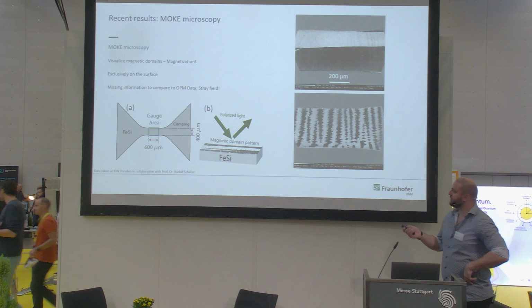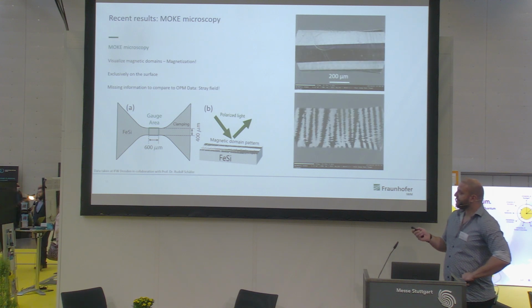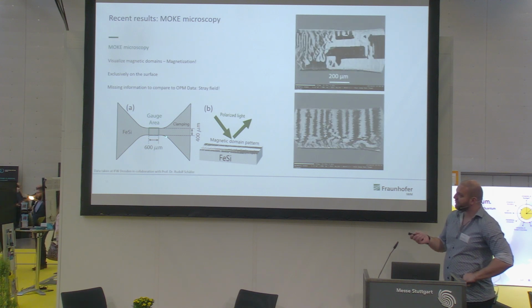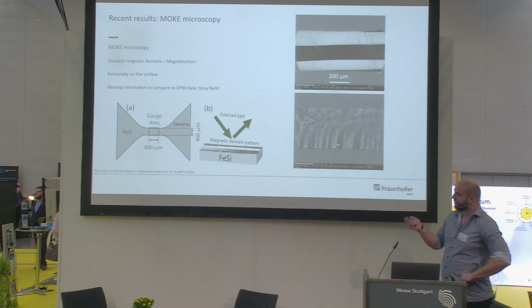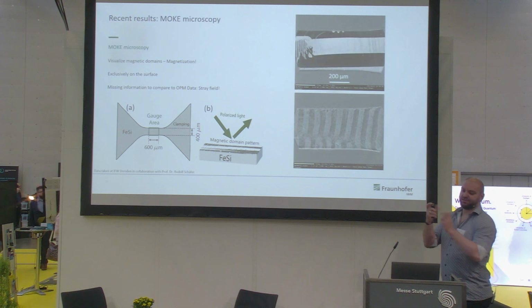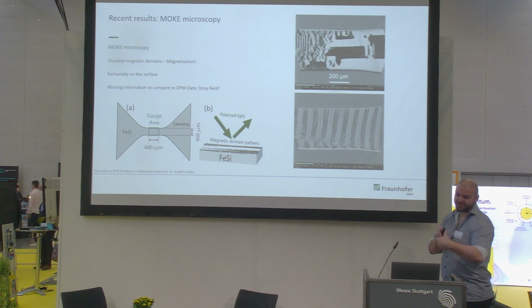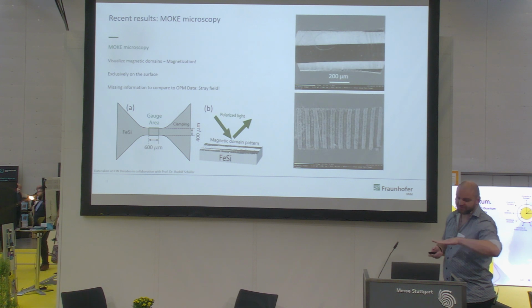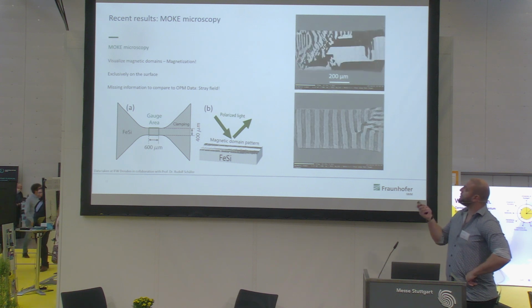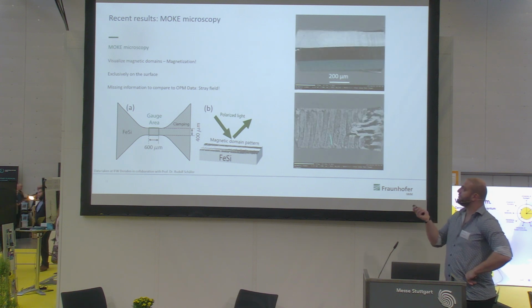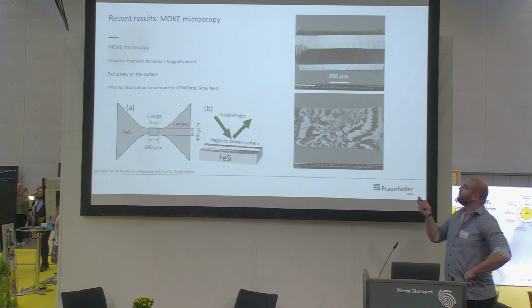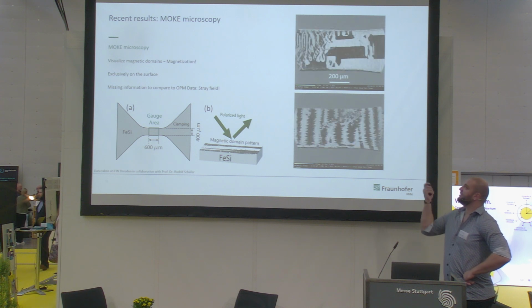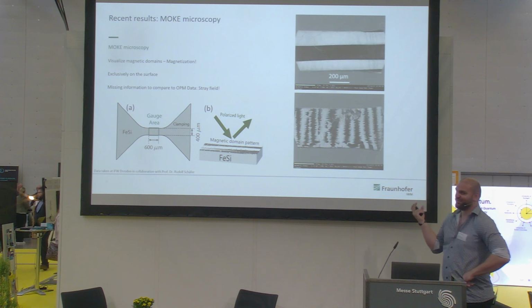So what you can see on the right is the gauge area of one of these samples. We shine polarized light, and it depolarizes because the light is interacting with the magnetization on the very surface of the sample. We go through our loading cycles, and you can see the magnetic domains shown in black and white. They evolve in a wild sort of fashion.